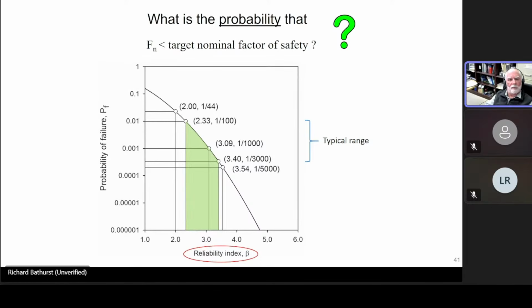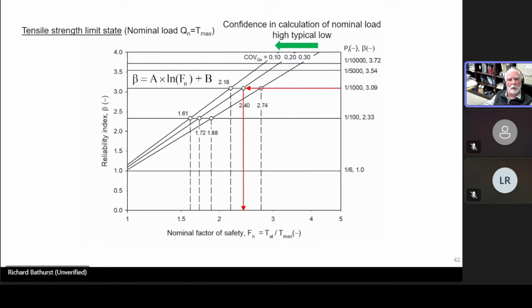Now, the advantage of this log linear equation that I showed you before is that if we have the statistics for model accuracy and estimates of the statistics for the input parameters, we can calculate reliability index versus nominal factor of safety. And on top of that, I can assign different levels of confidence in the calculation of the nominal load, and each one of those conditions will give me a linear line, as you see here. So the coefficient of variation of the nominal load varies here from 10% to 30%.